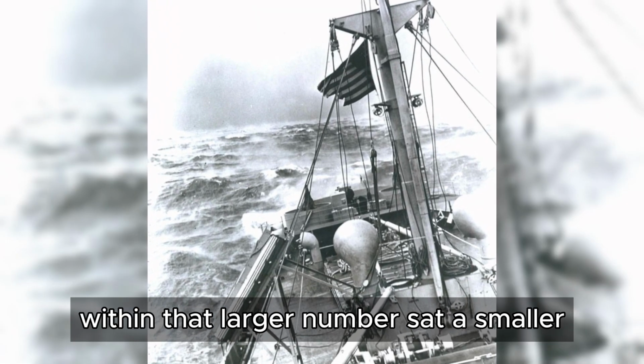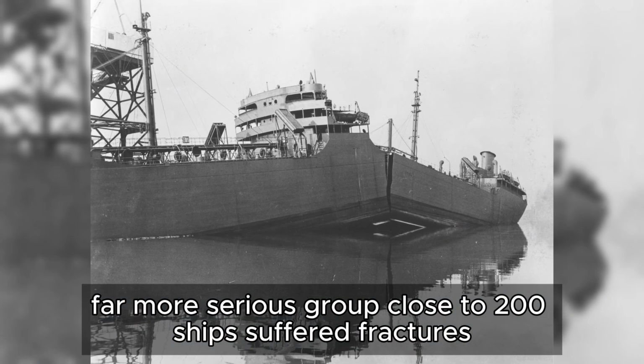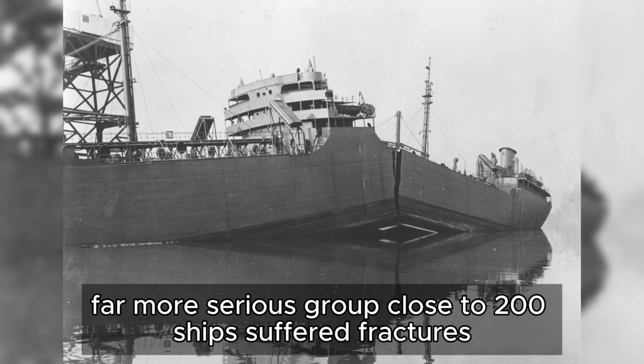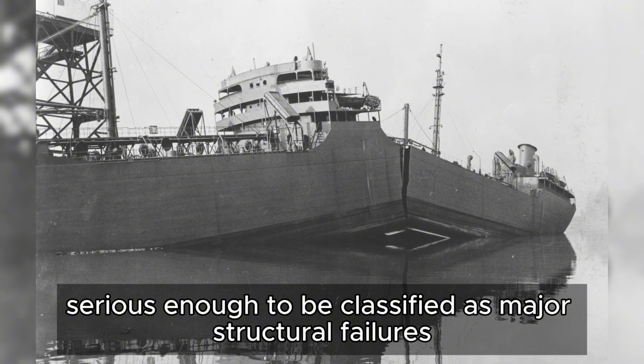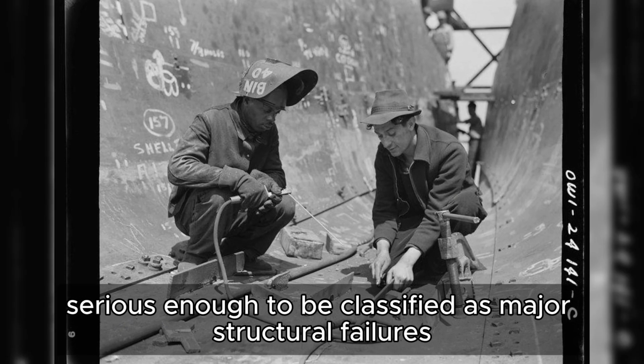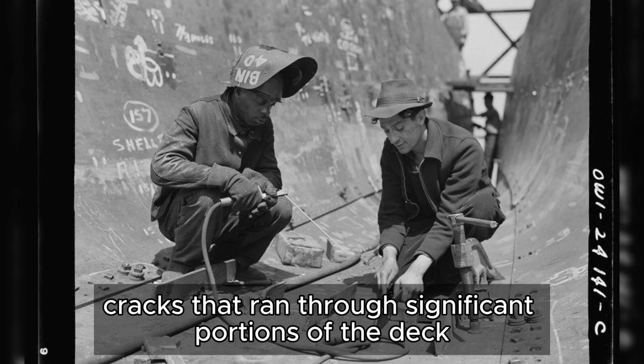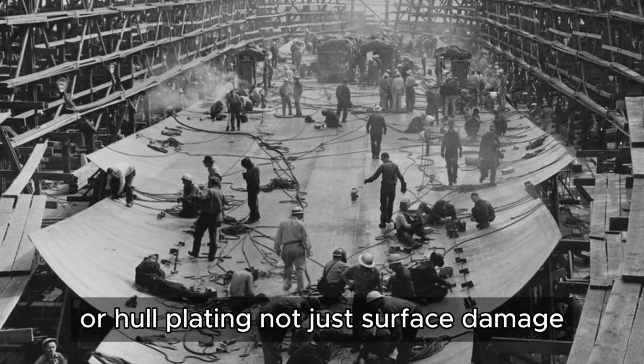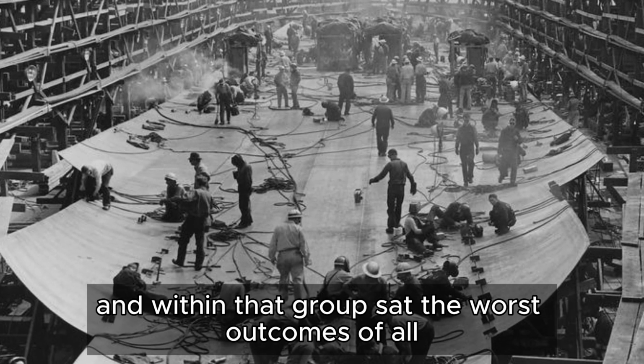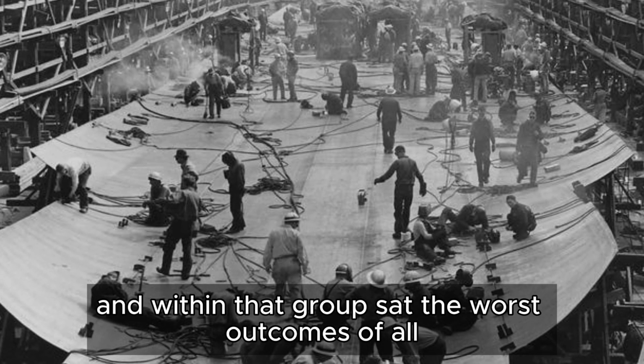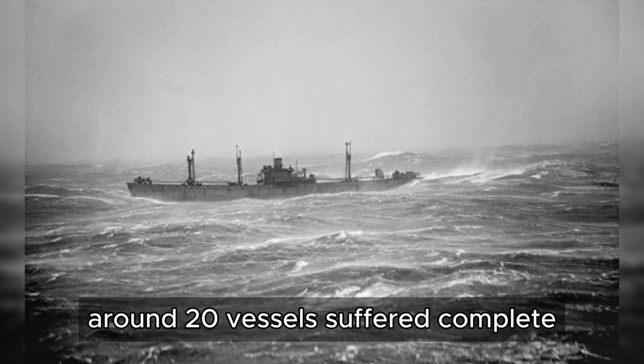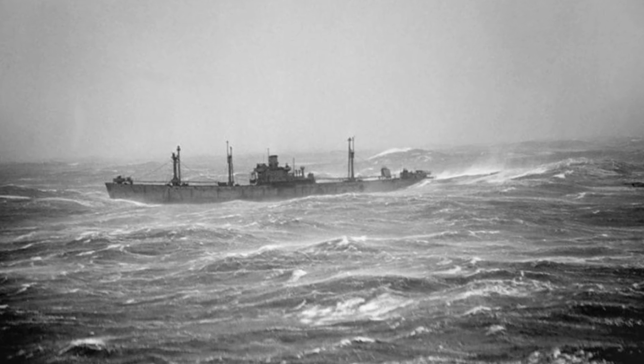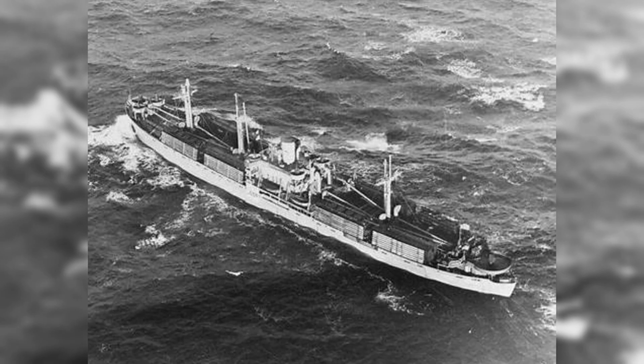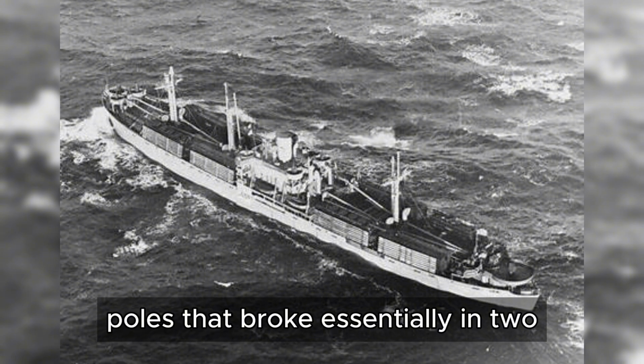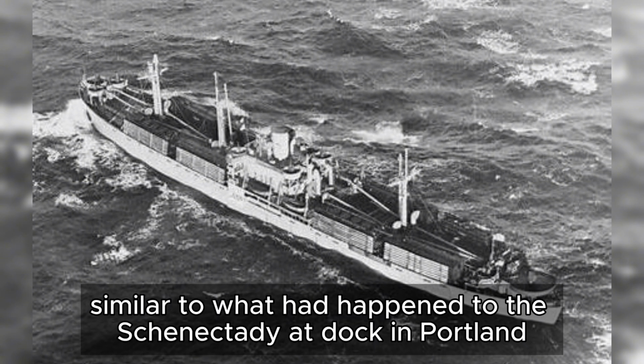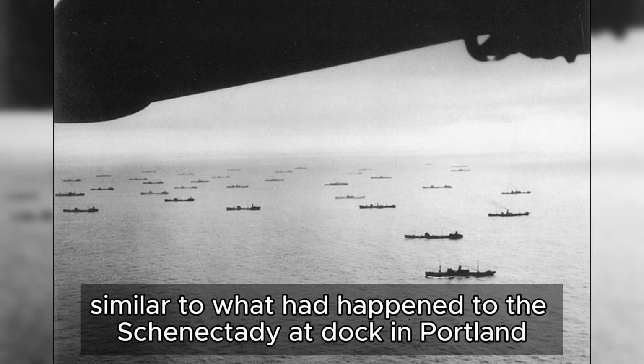Within that larger number sat a smaller, far more serious group. Close to 200 ships suffered fractures serious enough to be classified as major structural failures, cracks that ran through significant portions of the deck or hull plating, not just surface damage. And within that group sat the worst outcomes of all. Around 20 vessels suffered complete structural failures. Hulls that broke essentially in two, similar to what had happened to the Schenectady at dock in Portland.